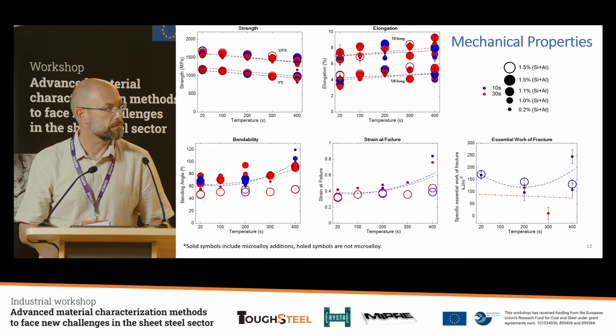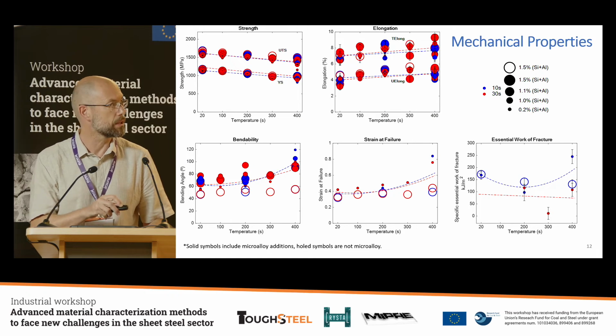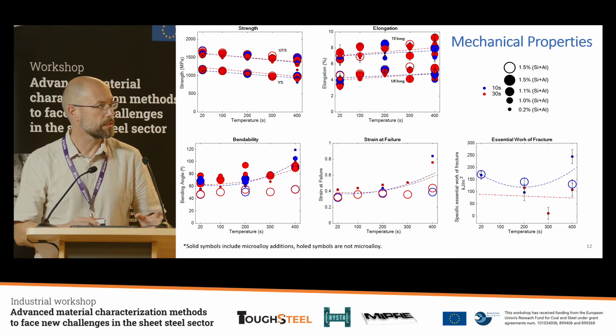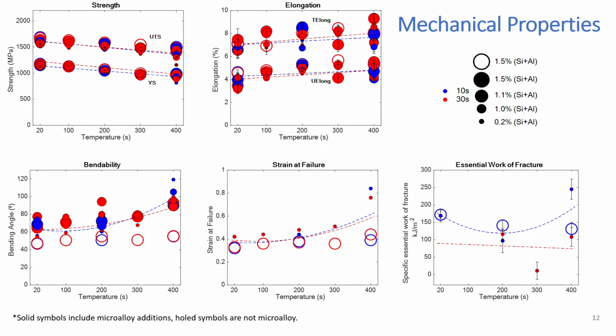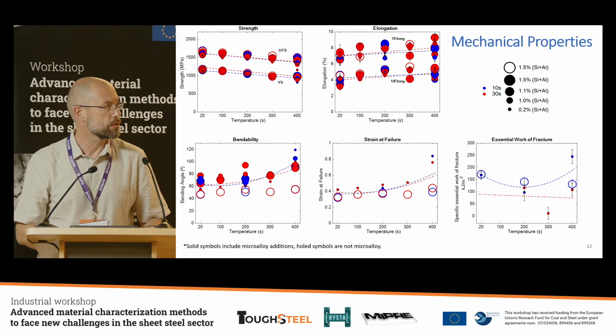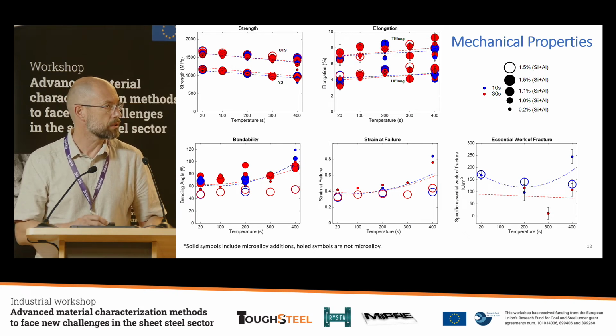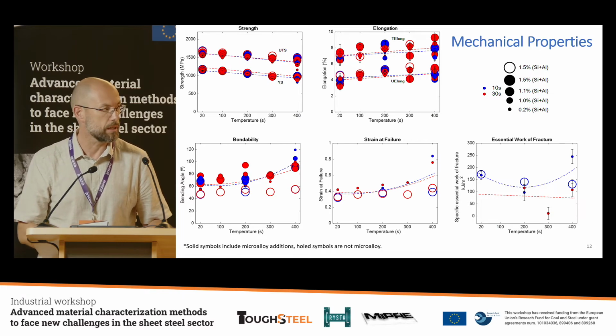The legend on the right hand side is over here. The size of the circles depends on the type of composition that we are using. And the colors, blue or red, mean the die closing times that we are going to have. So basically, there is an effect of increasing the tool temperature on the strength, which is decreasing the strength, and it also has some variations with the elongation. All of these results, I forgot to mention, correspond to the industrial steel, the PHS 1500. And we observe how the strain to failure, for example, and the bending angle improve with a shorter time for closure.